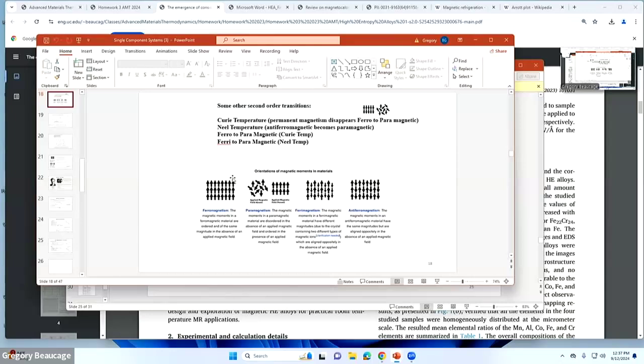So entropy is going to be related to the ordering of it. In the ordered state, the disordered state is what governs the delta S that goes with this. And they're using that delta S, like T delta S would be a change in energy, and that's going to be the energy of transition that it's going to be using to cool a refrigerator. So it's going to use this Curie transition to cause cooling in a refrigerator. That's the idea of this whole thing.